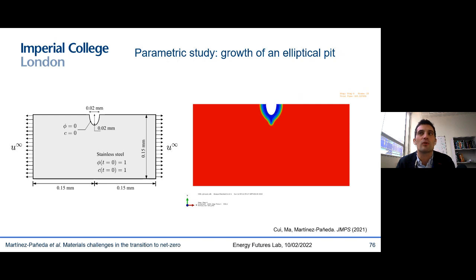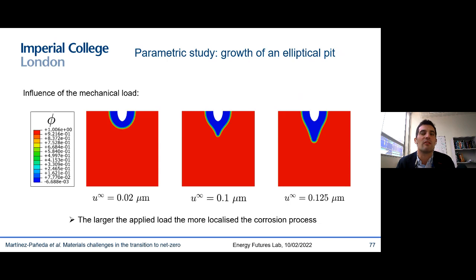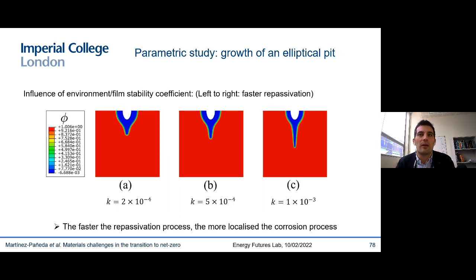I'm going to simulate here the corrosion of a plate with a semi-elliptical pit subjected to a uniform displacement. And if we look first at the influence of the mechanical load, what we see is that the higher the applied load, the more localized the corrosion process. And this is in agreement with expectations because a larger hydrostatic stress will sharpen the pit and increase its length. Now let's see what happens if we change that film coefficient. What you see is that it results in a faster repassivation from left to right, because if repassivation is fast, then corrosion process is more localized. In fact, you can actually see that we naturally recover the pit to crack transition that we have been trying to simulate for ages, I think.